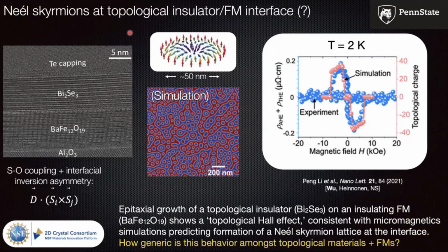So one of the ideas that we had explored a few years ago was, what if you put a topological insulator on an insulating ferromagnet? Then can you get these skyrmionic structures emerging at the interface? And in the transport, in this paper in Nano Letters, my colleagues and I were able to argue that the transport is strongly suggestive of the existence of these skyrmions. And this happens because of the spin-orbit coupling and the Dirac states.